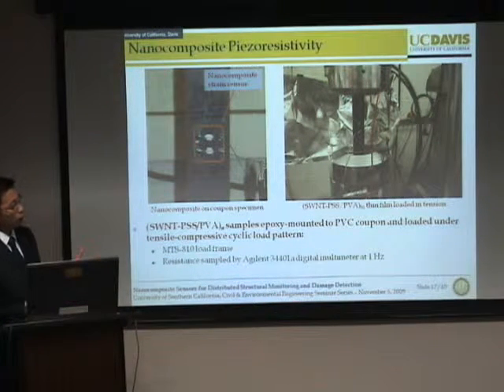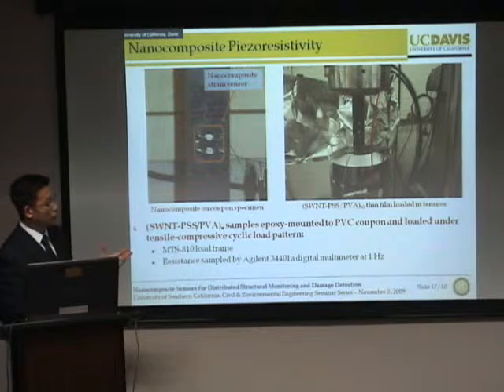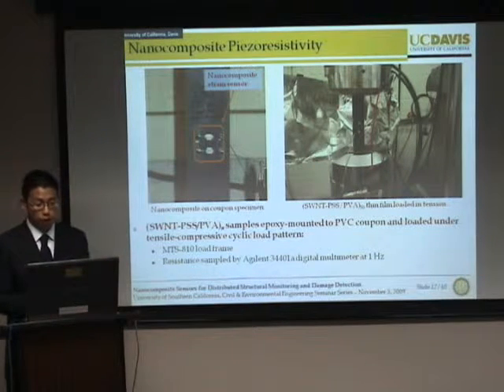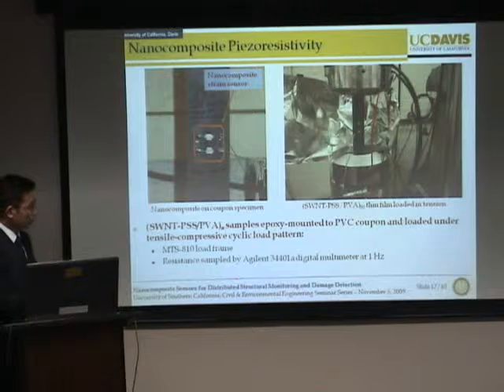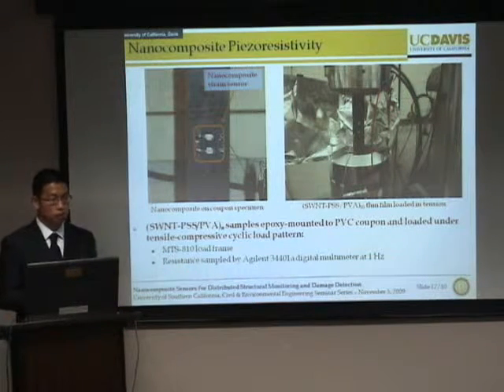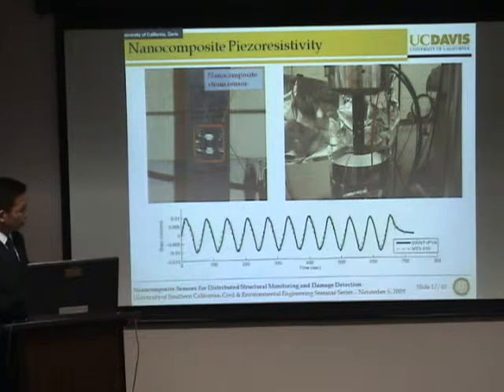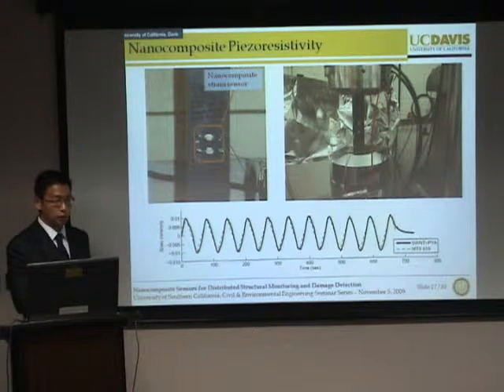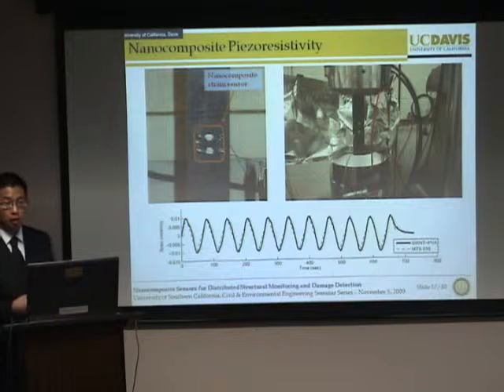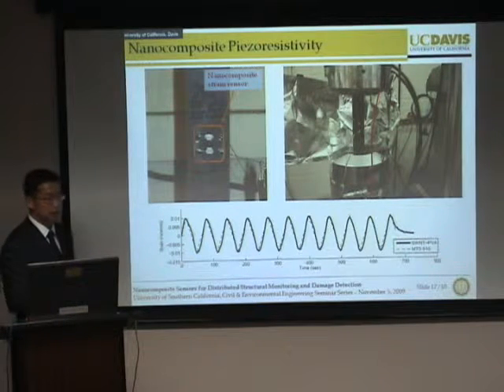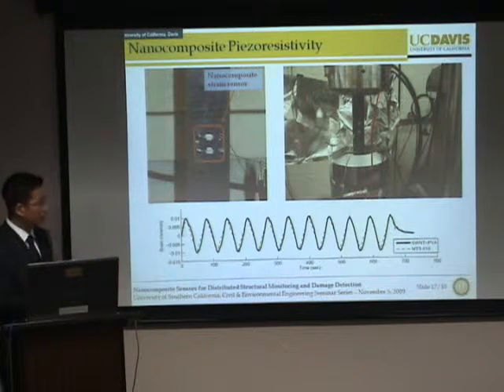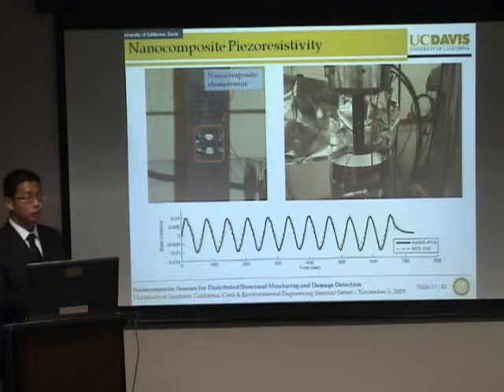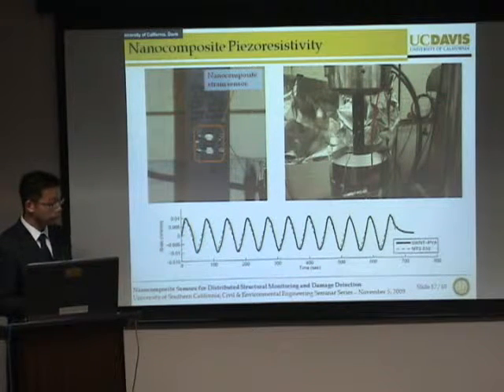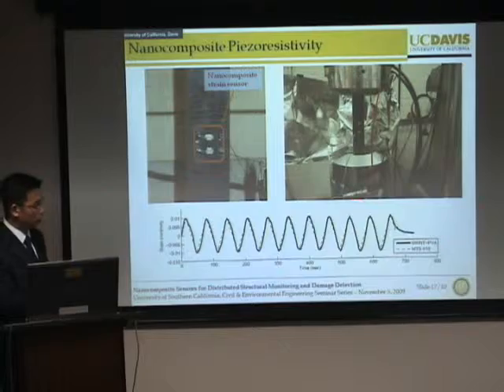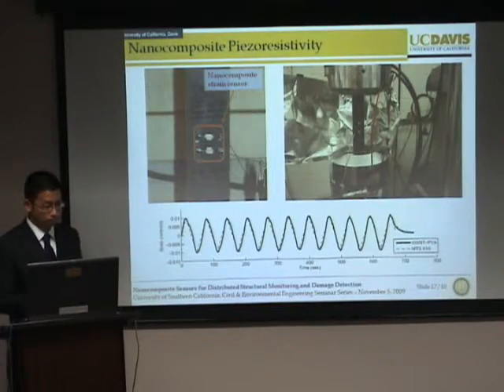Now in order to determine the strain sensing performance of this material, we can sample its resistance in real time using an Agilent digital multimeter. And from the results shown here, where we plot the overlay of the resistance of the material versus the applied strain, we see that this material behaves as an inherently good strain sensor. That is, the resistivity of the material increases in tandem with increasing strain. And furthermore, it's also repetitive.